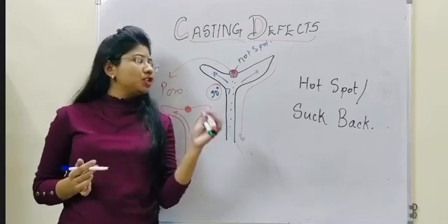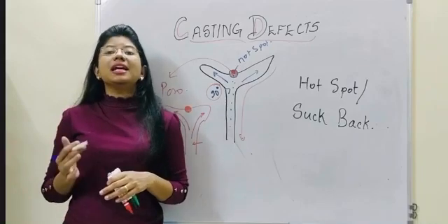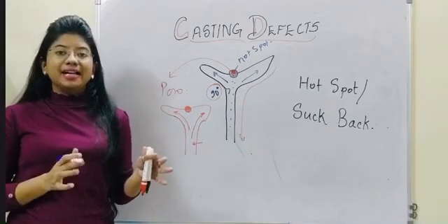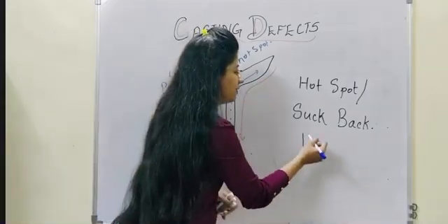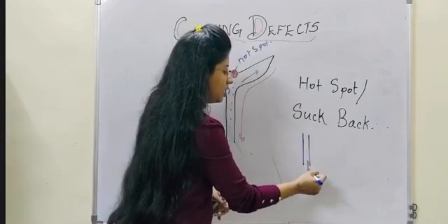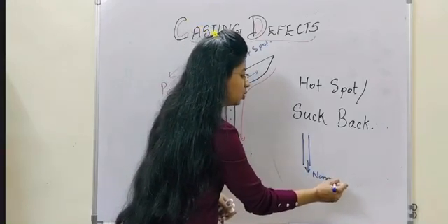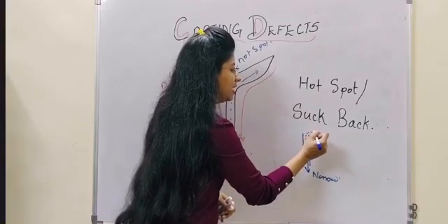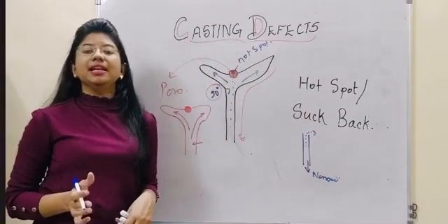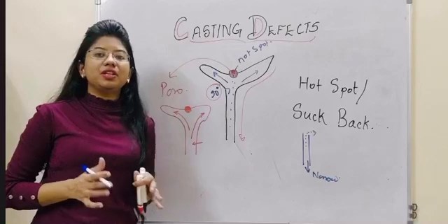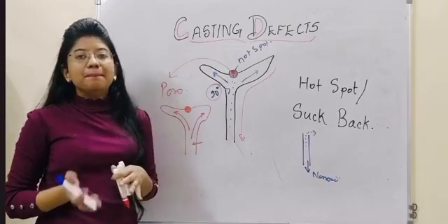In the first porosity, the localized shrinkage porosity, why had it happened? Because we used a very thin sprue. Because of the thin and narrow sprue, there is inappropriate entry of the molten metal. Secondarily, the metal quantity may be insufficient or the temperature low.